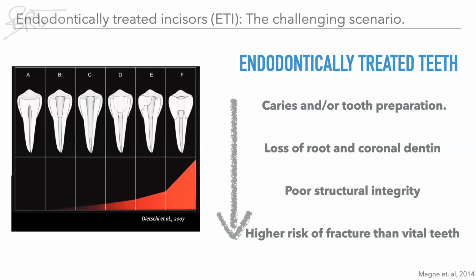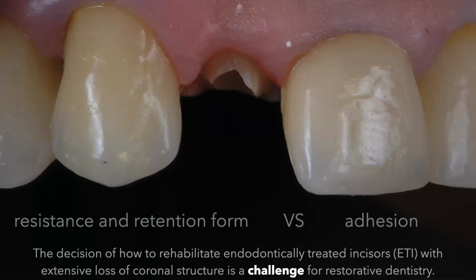So the problem is endodontically treated incisors in a challenging scenario. Those teeth are considered to have a higher risk of fracture than vital teeth because of their poor structural integrity, with loss of root and coronal dentin resulting from pre-existing caries or tooth preparation. Nowadays we have two choices: the resistance and retention form of the cast metal post and core, or the adhesive path using prefabricated posts. It's been proven by literature that the metal post's elastic modulus could even increase the risk of root fracture. Then a more biomimetic material was introduced to better copy the elastic modulus of dentin, the glass fiber post. The use of glass fiber posts has been associated with a lower incidence of root fracture.